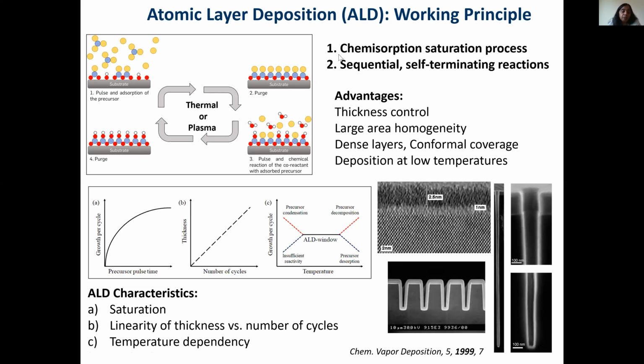So the main principle is you have a chemisorption and sequential self-terminating reactions. That's what I said, pulse and purge. And this is where you can have very good thickness control. Also, when you have high aspect ratios, that means the height to the width of the structures, then you can uniformly and conformally grow. And this is where, in microelectronics, where you have very deep trenches, ALD is playing a pivotal role.